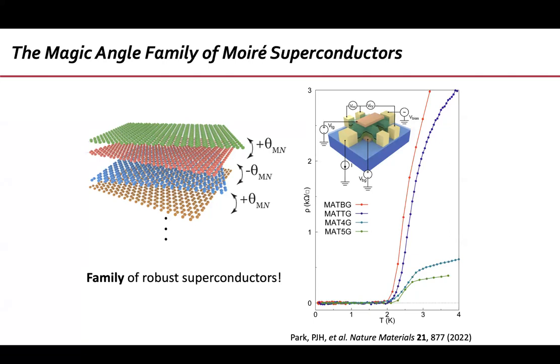And then why should it be the same strength? Because it's a matrix element between different orbitals, right? Some different combination of layers is doing the twisted bilayer graphene. You might think that would change the interaction. Yeah, so it changes the critical temperature a little bit, but not too much, and it tends to saturate. We weren't surprised, because we knew the Moiré wavelength doesn't change too much. It's all about the flat band physics. I would have loved it if it went much higher, but I would have been surprised if it did, given that the basic structure is very similar.